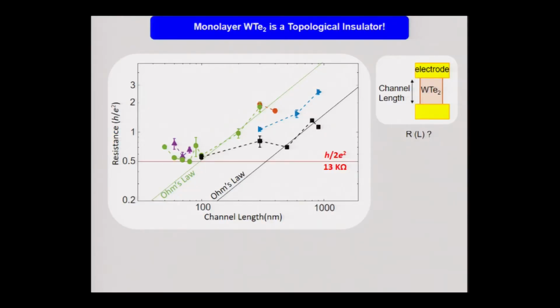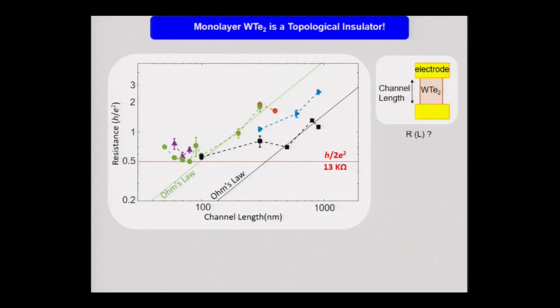But this is not the case when you fabricate monolayer tungsten ditelluride in the short limit. If the length of the material is about a few hundred nanometers or more, then with longer length, you do see Ohm's law behavior: longer material, higher resistance. But once you go to a short edge limit, below 100 nanometers, this behavior deviates from Ohm's law significantly. The resistance does not decrease anymore. It saturates to a number that's determined only by fundamental constants, where h is the Planck constant and e is the electron charge. This is one of the key hallmark signatures of a quantum spin-Hall insulator.